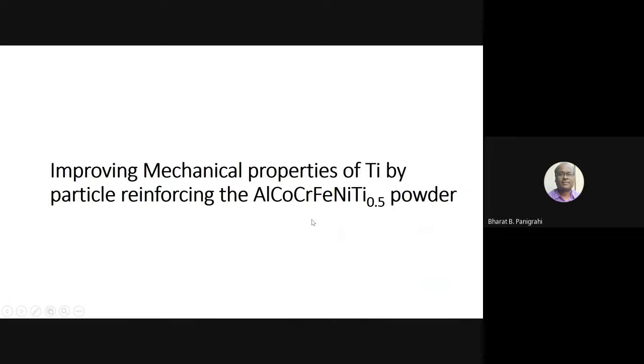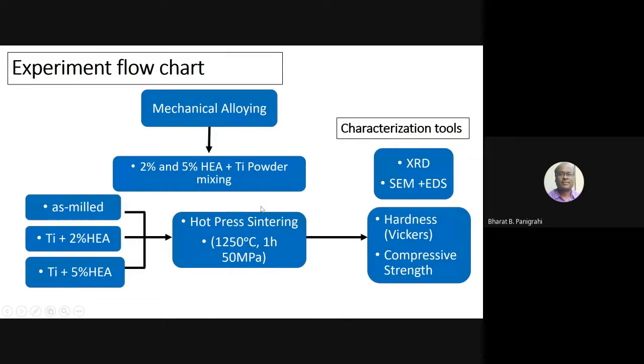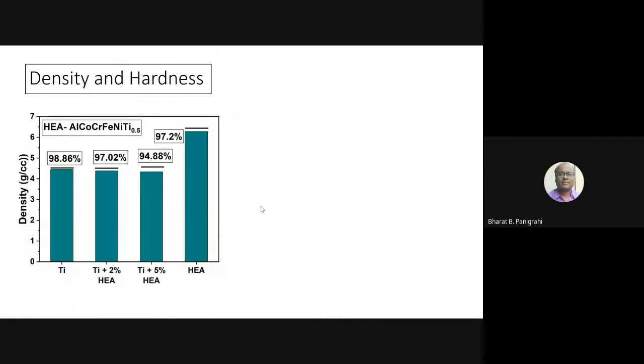There is another technique we tried: the development of a composite using this particular alloy as a reinforcement in pure titanium. We use powder metallurgy techniques, of course. So you have a pure titanium powder, and in that pure titanium we are using HEA as a reinforcement. We have chosen a high strength, high entropy alloy, which we are adding at 2% and 5%. This pure high entropy alloy has a strength this much, sintered, and of course their sintered density is more or less the same.